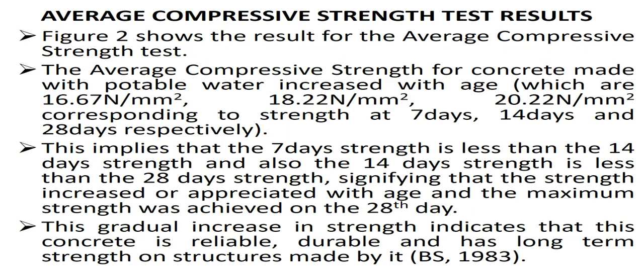Figure 2 shows the result of the average compressive strength test. The average compressive strength for concrete made with potable water increased with age, which are 16.67 Newton per mm square, 18.22 Newton per mm square, and 20.22 Newton per mm square, corresponding to strength at 7 days, 14 days, and 28 days respectively. This implies that the 7-day strength is less than the 14-day strength, and also the 14-day strength is less than the 28-day strength, signifying that the strength increased or appreciated with age, and the maximum strength was achieved on the 28th day. This gradual increase in strength indicates that the concrete is reliable, durable, and has long-term strength on structures made with it.